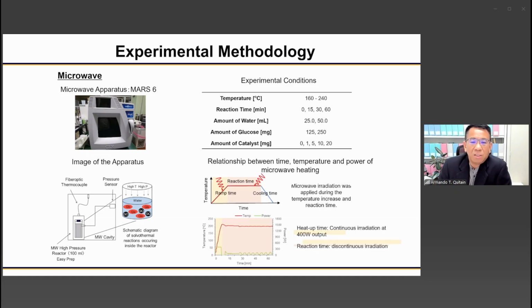And this is an example of how we can achieve the reaction temperature by ramping it up at first, normally about 15 minutes, followed by holding time for the reaction to occur. We normally apply a microwave power of about 400 watts, but this can be higher depending on the materials or even lower than 400 watts.